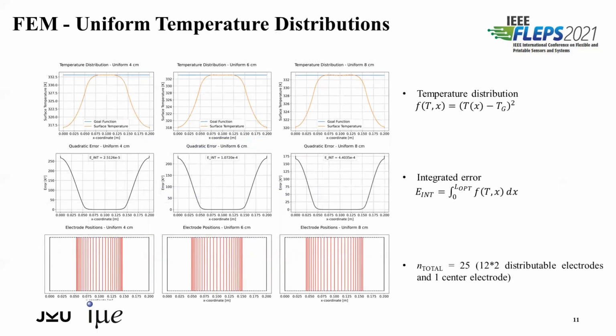This slide shows optimization results for 3 different optimization lengths of 4, 6, and 8 centimeter. The top row shows the temperature distribution along the total substrate width. The center row shows the quadratic deviation from the goal temperature, and always as an inset, you see the value of the total integrated error. The bottom row shows the distribution of the electrodes to reach this temperature distribution from the top row. We can see here, for each optimization length, the temperature is now homogeneous inside this optimization length. The total number of distributable electrodes, in this case, was 25 for each optimization.